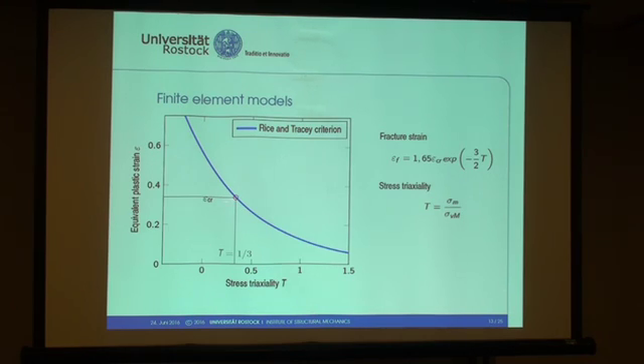It's calibrated by the value epsilon critical. This is the failure strain at T equal 1/3, uniaxial tension, and it is implemented in finite element software by a damage integral.